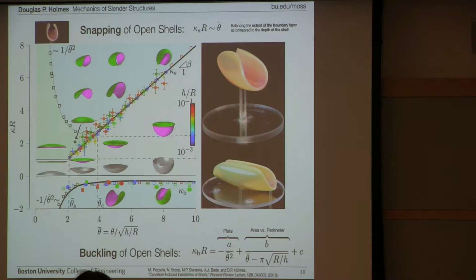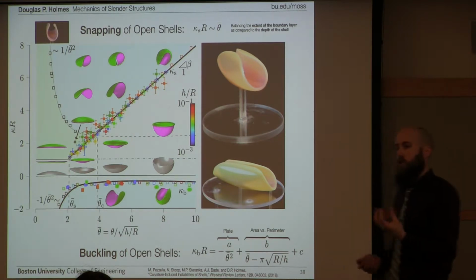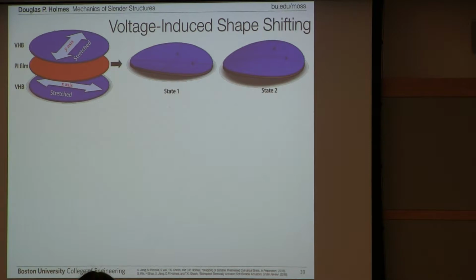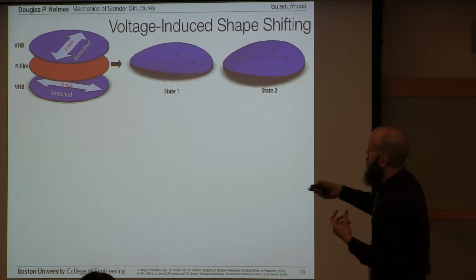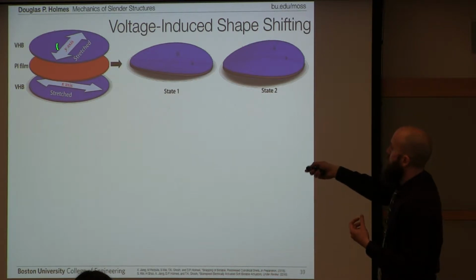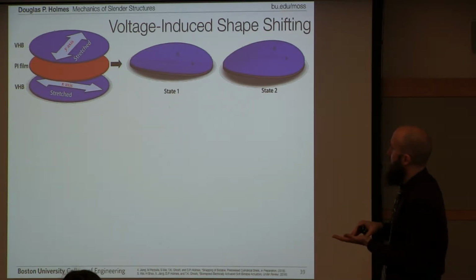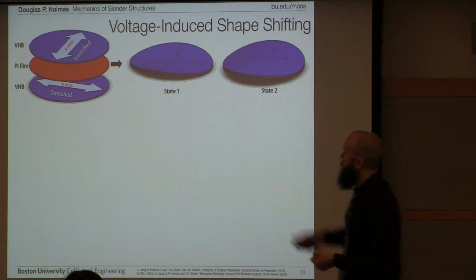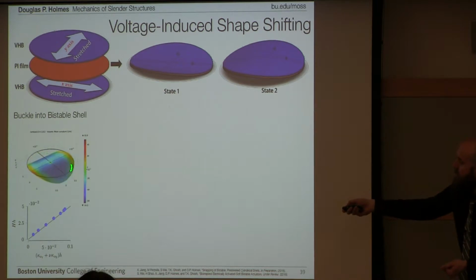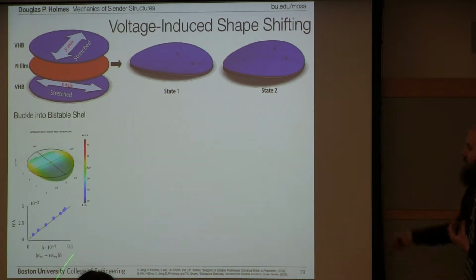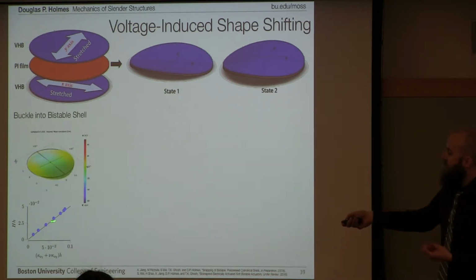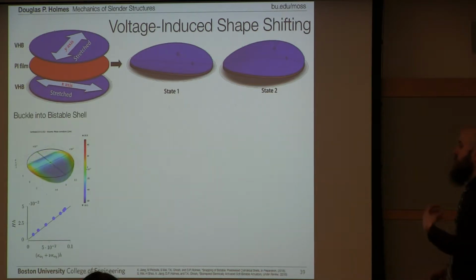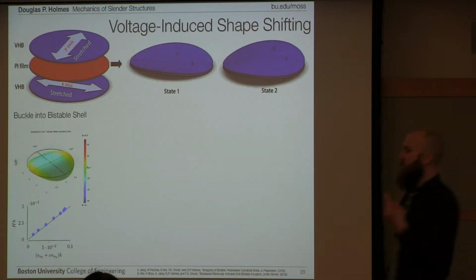So why do you care about this? Well, one of the most promising ways to make actively morphing structures is to use voltage as your stimulus. And voltage can impart a natural curvature just like anything else. If you take a dielectric elastomer and, for instance, make a tri-layer where you stretch the dielectric elastomer one way here, and you mount it into a stiff middle layer, this will cause this structure to buckle. So we're looking here at simulations of this type of structure buckling into a bistable shell. The amount of stimulus you need to get it to buckle dictates how curved your shell is going to be. And so we can use that phase map that I showed you on the last slide to predict the shape of our bistable shell.